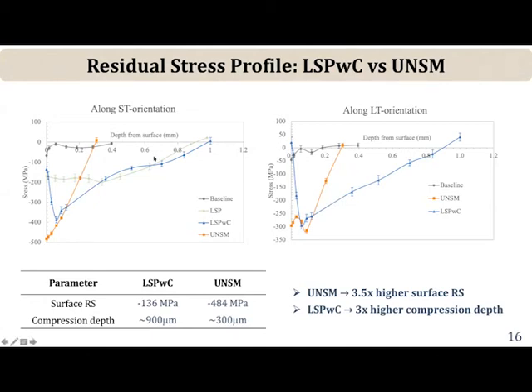And in fact, you get some very remarkable results when you combine the two techniques, because you can get high compression at the surface like UNSM. If you do LSP first and then followed by UNSM, or do UNSM first followed by LSP, you can get fairly high compressive residual stresses at the surface. But then when you combine the two processes, you can get much deeper. So in fact, one can make this profile look something like this by combining the two processes. But regardless, you can see that UNSM can lead to much higher surface compressive residual stresses, but the depth of compression is somewhat lower than the case of laser peening.